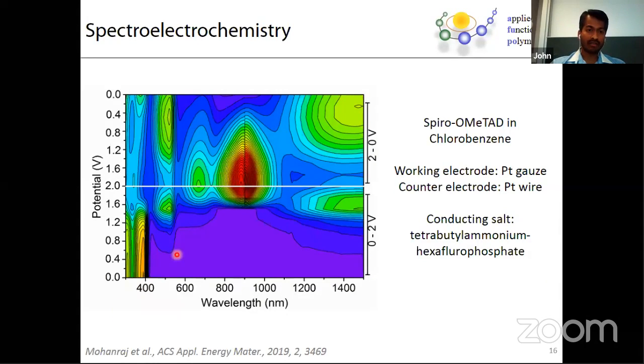But the important take-home message from this experiment is that when you oxidize a system, you see a new species at around 520. When you highly oxidize a system, then you see a new species which absorbs at around 700 nanometer, also at around 900 nanometer. So keep it in mind, because it's going to help you in the next slides.